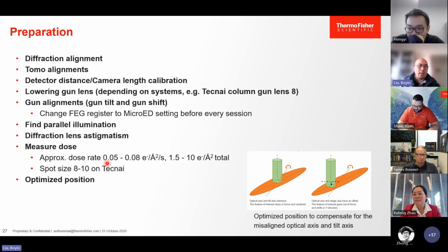Measure the dose rate, usually between 0.05 to 0.08 electrons per angstrom squared per second. Overall dose may usually be between 1.5 to 10, sometimes it can go up to 25 depending on samples. Spot size between 8 to 10 on the Tecnai column, and also you need to do the optimized position calibration. Optimized position is to align the optical axis with the tilt axis so that they are perpendicular to each other. If they are not perpendicular, you have some image shift. Even if you're at the central height, your crystal will slowly drift away when the stage tilts.